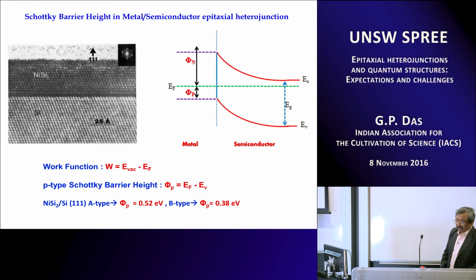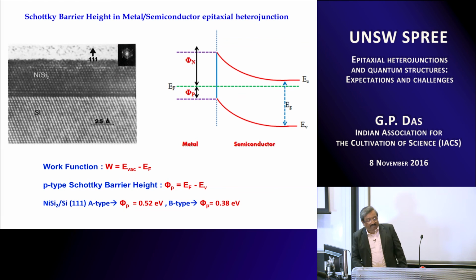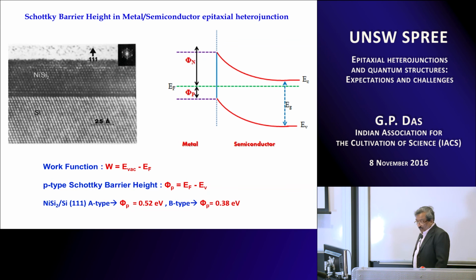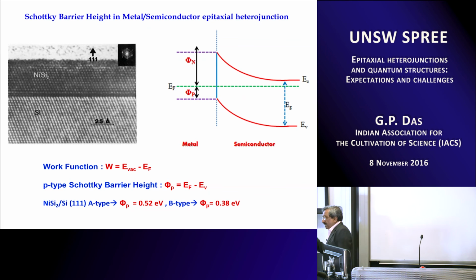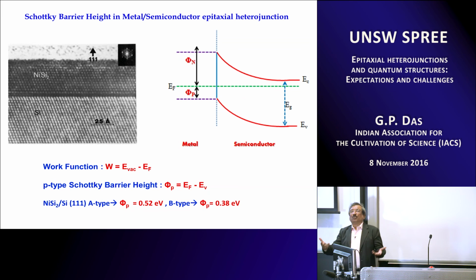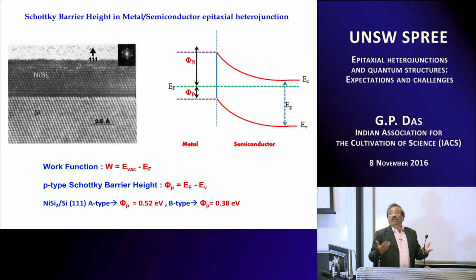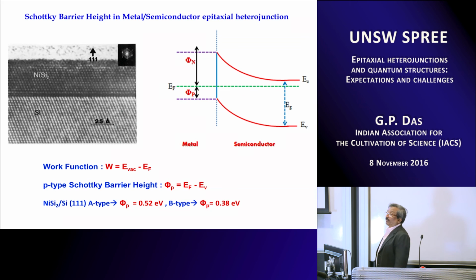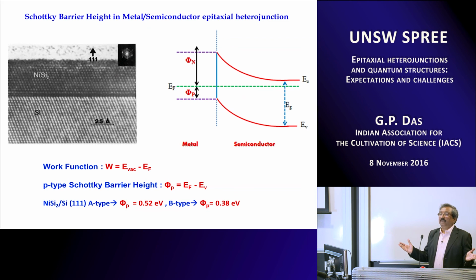Now why am I discussing this? I am discussing this because of a very intriguing observation in Bell Labs way back in the late 80s, that in this particular interface, epitaxial interface of nickel disilicide on silicon, depending on what is the orientation at the interface, it's called A type and B type, the Schottky barrier height changes enormously. The p-type Schottky barrier height for A-type NiSi2 to silicon 111 interface is 0.52, whereas for the B-type it is 0.38. Imagine that I am not changing the semiconductor, I am not changing the metal. So there is no question of my changing the work function, but still the Schottky barrier changes by as much as 0.14 electron volt, which is something which could not be explained at that time.